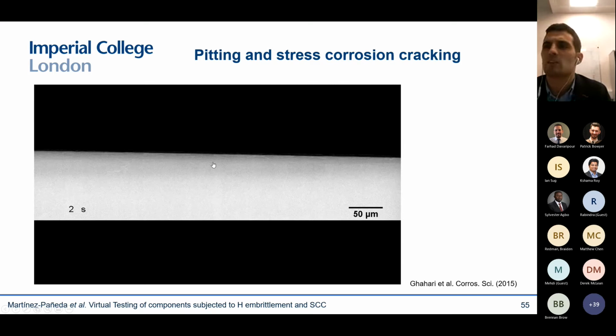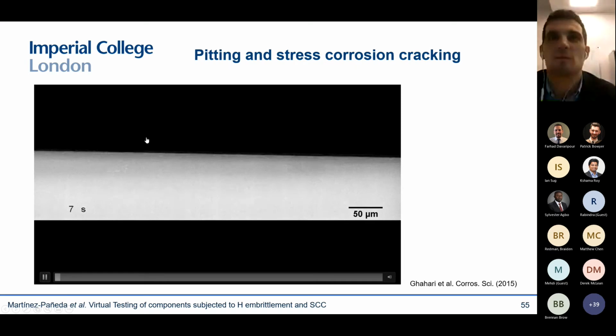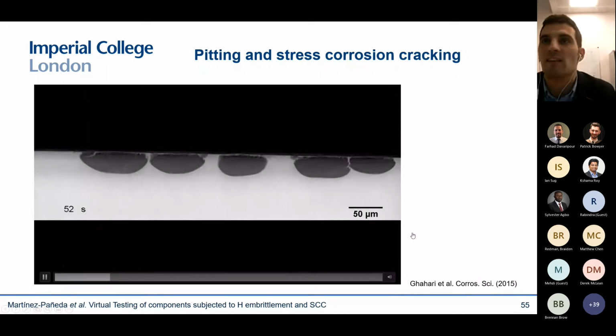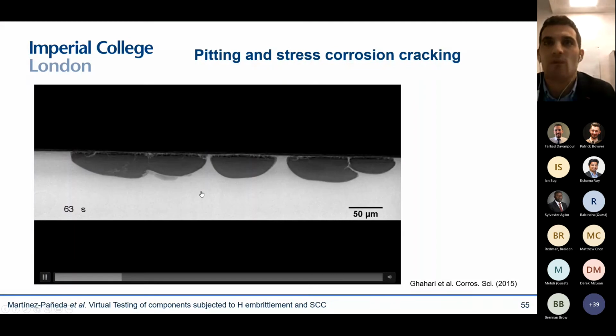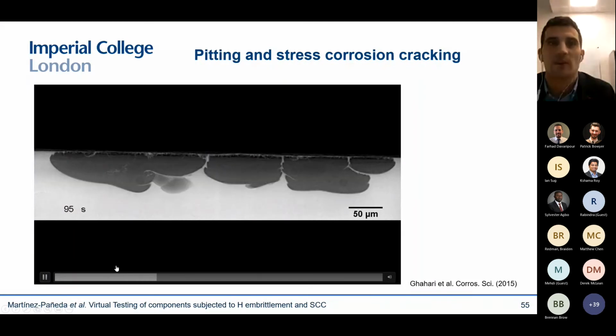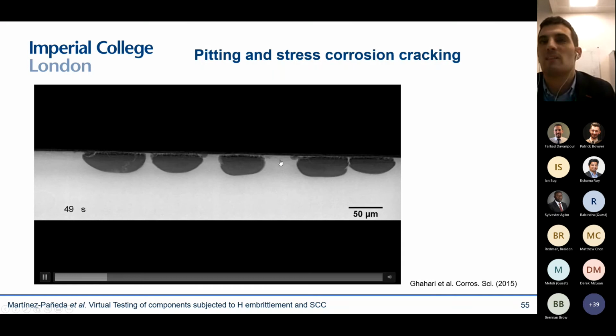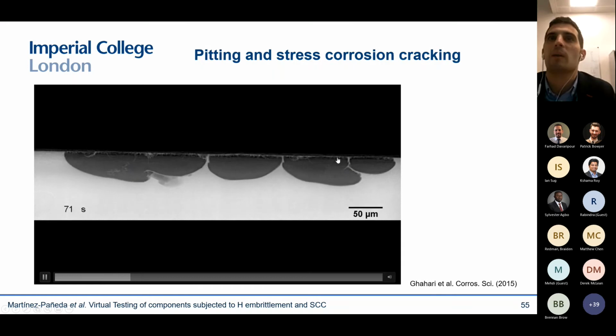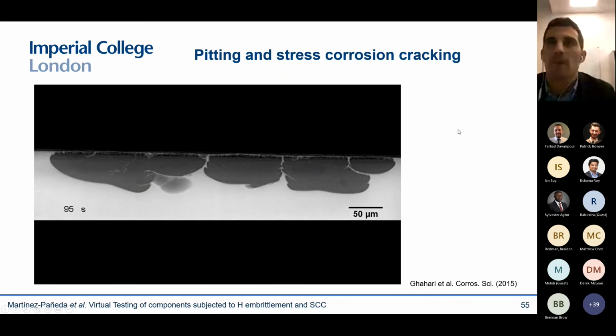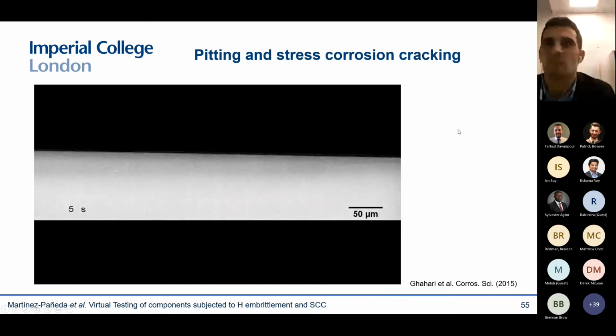And it has many similarities with hydrogen embrittlement, right? It is an interfacial problem. It is a multiphysics problem. So it is something that we are interested in showing that we can do with computers, but again, it comes with multiple challenges. One of the challenges is the interface nature of the problem, right? You can see here, these are pits in stainless steel as measured using X-ray. So this is a synchrotron, and you can see, of course, that it's very complex phenomena. You have pits and nuclei that start growing, and eventually they coalesce with each other. So mathematically and computationally, it's quite a nasty problem.